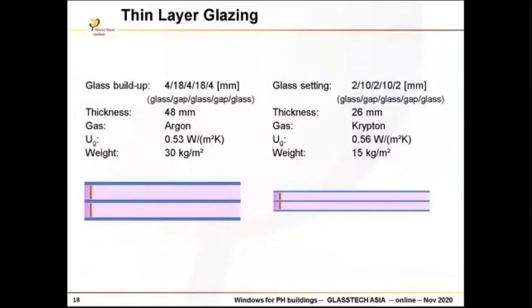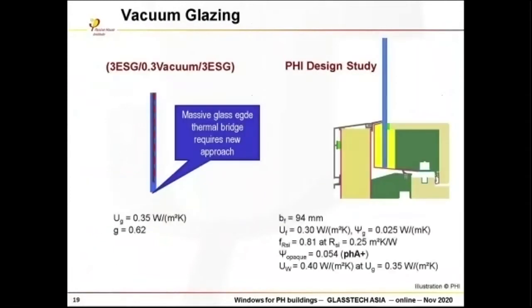Okay, another point is if you want to go for very slim and lightweight glazing, you can do. This is a newer development, but please note, if you go for very small gaps, you need to go for krypton instead of argon. Argon and a wider gap is a cost-effective solution, but it's a little more weight here. The other point is vacuum glazing. This is a promising development in the recent few years, but please check the rebate and the edge of the glass has a very large thermal bridge, and therefore, and you see it on the right-hand side, you have to have a special frame to get the heat losses at the glass edge as low as possible.